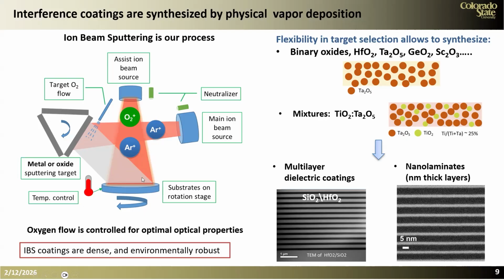What this process has is that it produces coatings that are very dense. They almost have the density of the crystalline material, and thus they are environmentally robust. Using this system, we can grow binary oxides such as hafnia, tantala, germania, scandia, and so on. But we can also make mixtures. And the ability to make mixtures is very important for the coatings for LIGO.